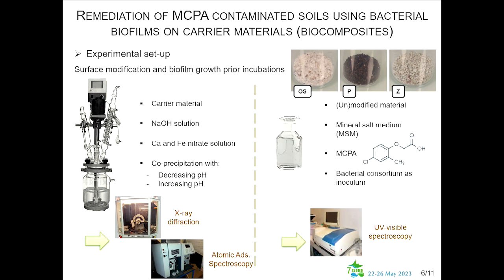After that, on modified and non-modified materials, we try to grow biofilms. This is made in a mineral salt medium that contains MCPA, an herbicide, that will be studied during the whole procedure, but is also the carbon source for microorganisms. And we introduce a bacterial consortium as inoculum. The efficiency of the procedure and of the formation of biofilms is checked thanks to the remaining concentration of MCPA in the solution, thanks to UV-visible spectroscopy.